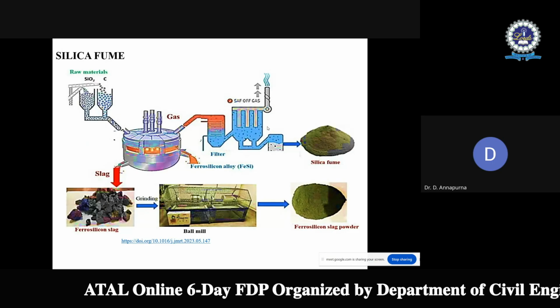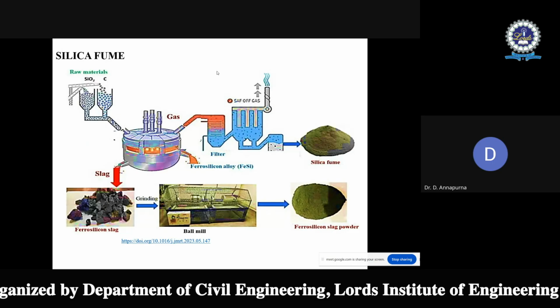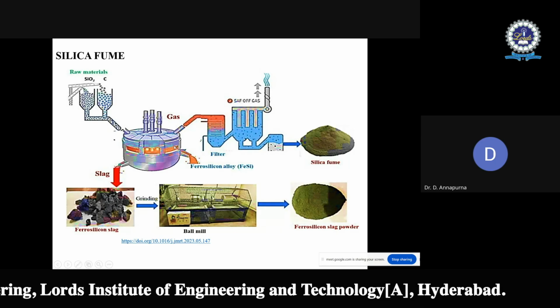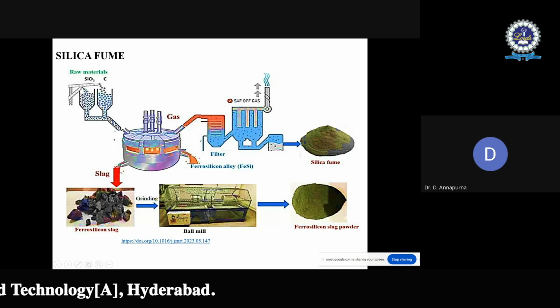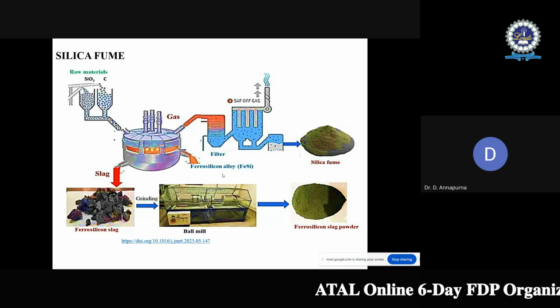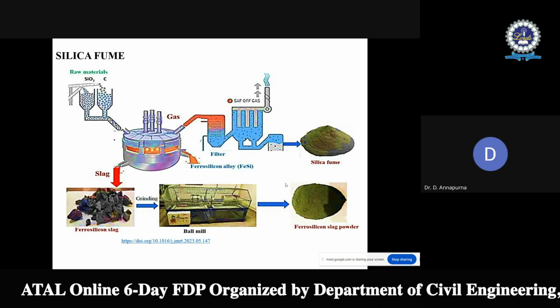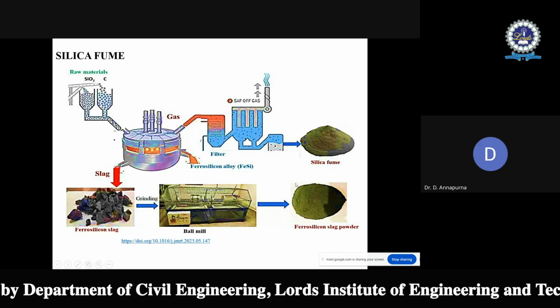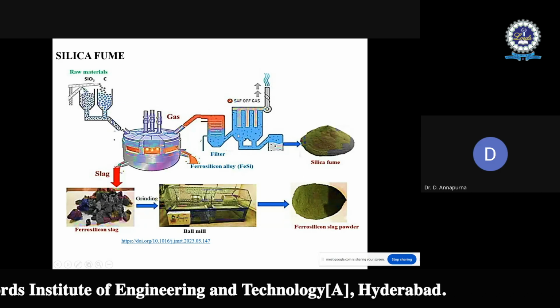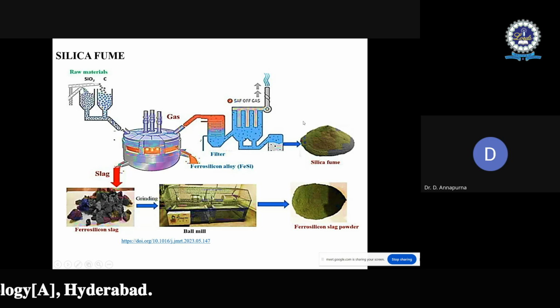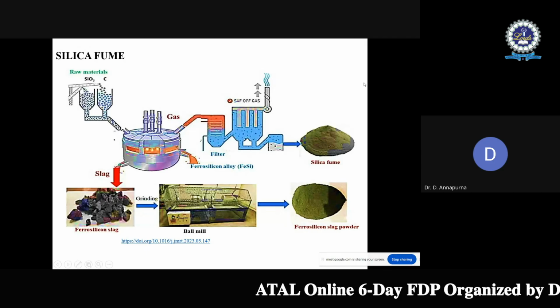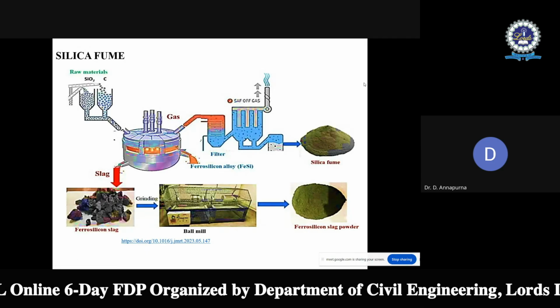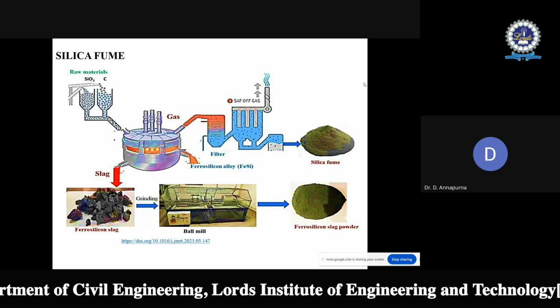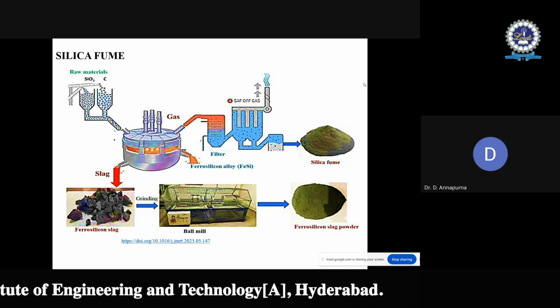Next one is silica fume. Silica fume is a byproduct from the silicon or ferrosilicon industries. Here quartz is heated with wood chips and coal in an electric furnace at a high temperature of 2000 degrees Celsius to reduce the oxygen content in silicon oxide. Then the fume condenses and oxidizes at the top of the furnace to form silicon dioxide. That is how silica fume is generated, subjected to a huge amount of temperature, and it is ground to a fine powdered form. The particle size is very, very small compared to all the other pozzolanic materials. It is very rich in silica. The silica content of silica fume will be very high.